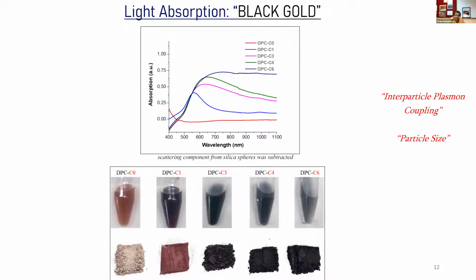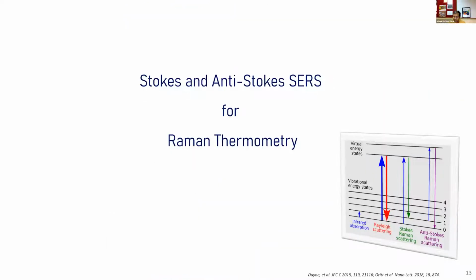It's just the gap between the particles that allowed them to undergo plasmonic coupling, and you can now see the light absorption behavior. So with cycle increase, you see now it becomes a broadband light absorption from visible to near IR light. That means now you can harvest a large number of solar photons, and those solar photons can be converted into either hot electrons or heat. We wanted to test whether we really produce the heat. What is the surface temperature that one can achieve when these hot electrons undergo relaxation by electron-phonon coupling?